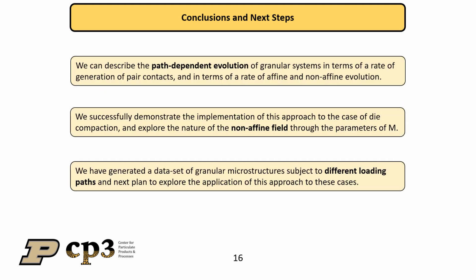In conclusion, we can describe the path-dependent evolution of granular systems in terms of a rate of generation of pair contacts and in terms of a rate of affine and non-affine evolution. We furthermore successfully demonstrate the implementation of this approach to the case of die compaction and explore the nature of the non-affine field through the parameters of M. Finally, we have generated a dataset of granular microstructures subject to different loading paths and next plan to explore the application of this approach to these cases.